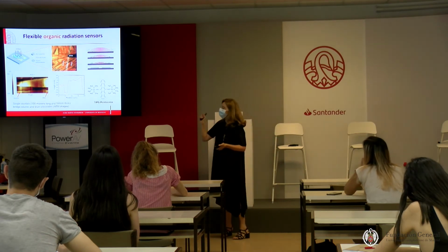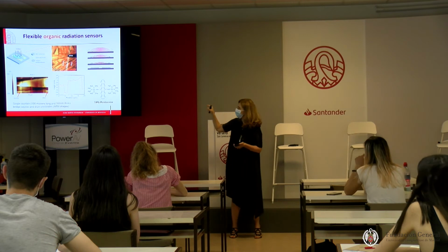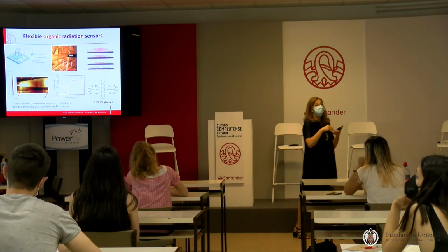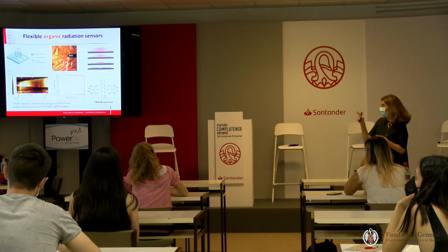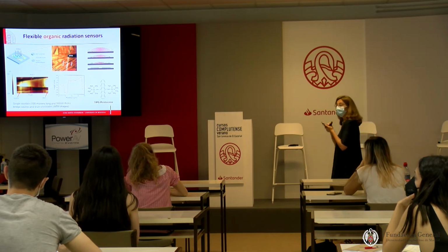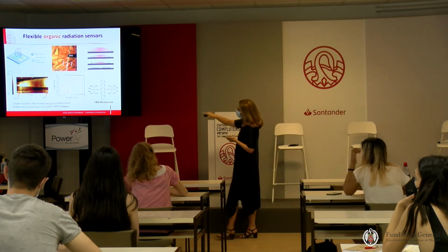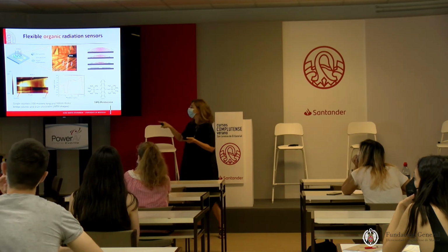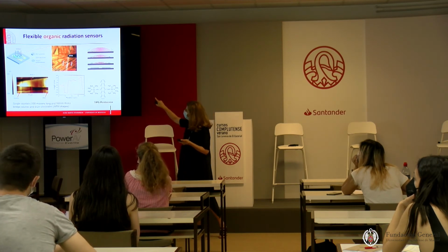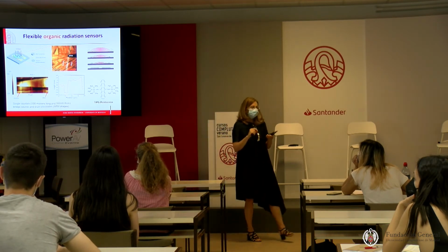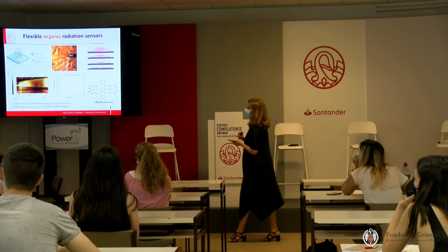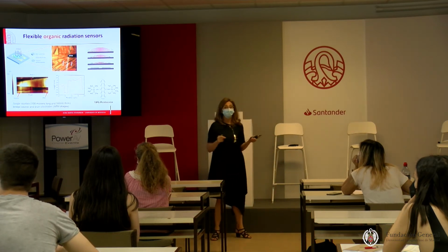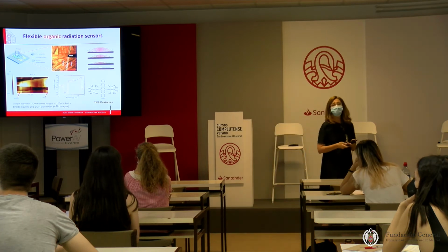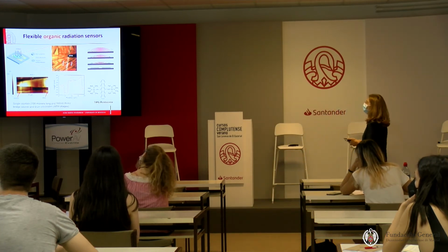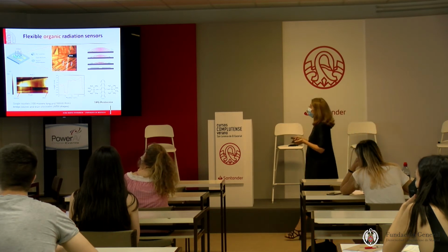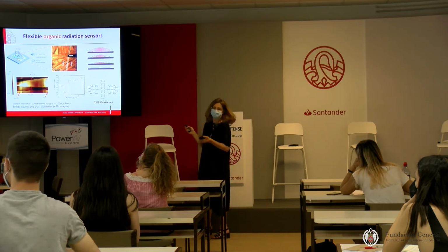Here is an image of the film that we deposit. On the left-hand side, you see the drying out procedure when the solvent of the solution evaporates, and it leaves this microcrystalline structure. Each crystal that you see imaged in an atomic force microscope, in the bottom one, the top one is an optical microscope. You see that the dimensions are thickness about 100 nanometer, length about 100 micron. So they're really thin, multiple crystals. The molecule we're using is called TIPS pentacene. As you see, it's based on carbon, hydrogen, and silicon. It has 2 silicon atoms.